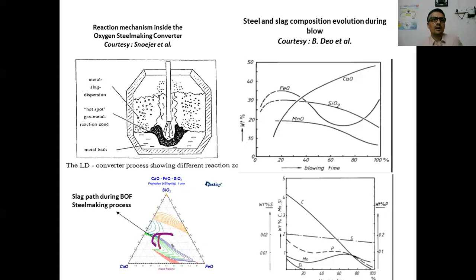So the entire process involves slag metal reaction, that means the evolution of slag with time as the lime dissolves. If you look at the evolution of steel and slag composition during the process, in the initial part of the process, FeO increases. It increases because the process is being blown with a higher lance height. The higher lance height in the initial part leads to the formation of more and more FeO. And the FeO is required for the dissolution of lime. Why? Because if you look at the CaO, FeO, SiO2 phase diagram, you will find that lime is not going to dissolve unless you form FeO.